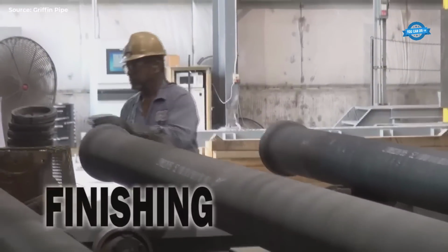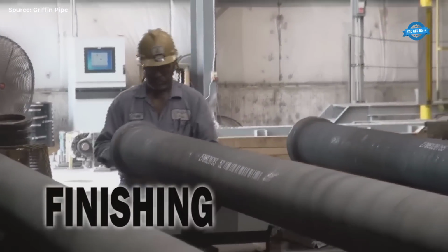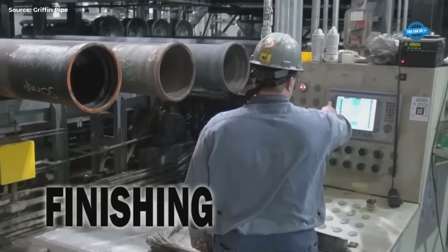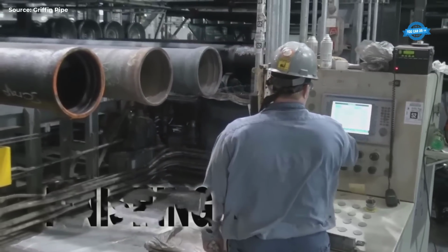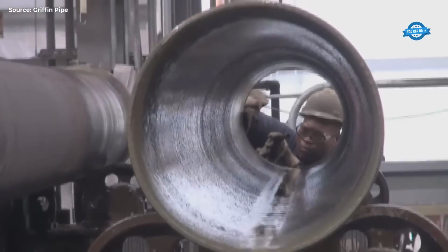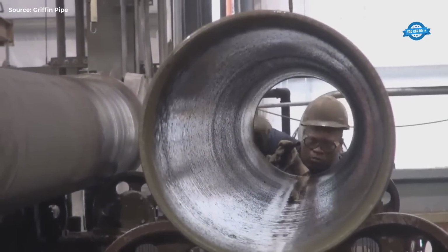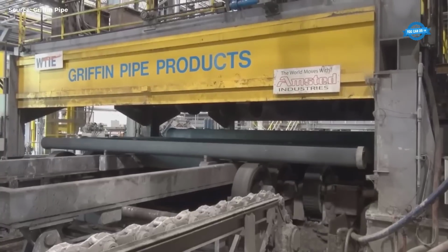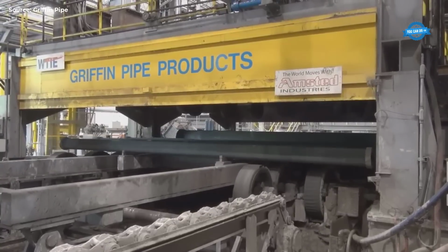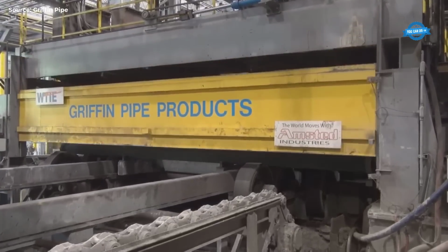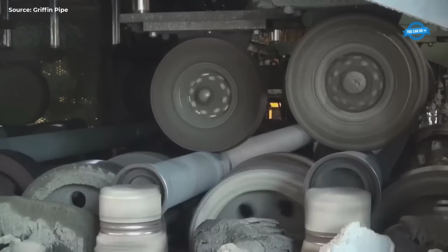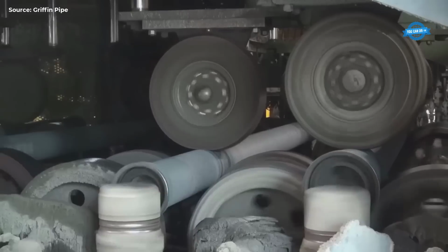Lining and finishing. Once annealed, the pipe undergoes extensive inspection and testing. After cooling, each pipe is inspected for visual defects and gauged for proper dimensions. The pipe is also weighed to ensure it meets minimum weight standards. Following weighing, the pipe is bar-coded with information regarding weight and class. The pipe then undergoes a water pressure test, and samples are taken to determine mechanical properties such as tensile strength, yield strength, elongation, and impact strength.